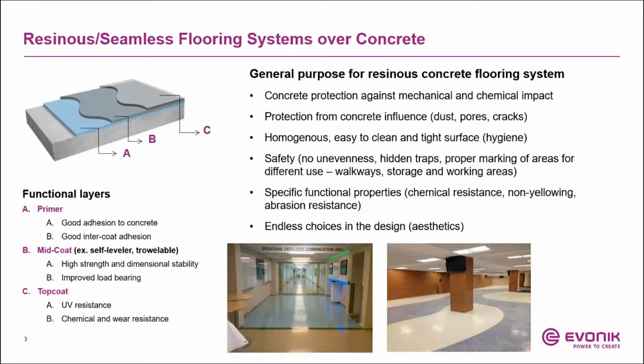As you see here, it's an example of a type of seamless flooring system. As you see, it is really a multi-layered type of coating. It's not just one layer of coating applied to concrete. The reason is, you start out with a primer. You want something that has good adhesion to concrete, and also should have good intercoat adhesion, so subsequent layers can be put on top and stick well to the concrete as well.